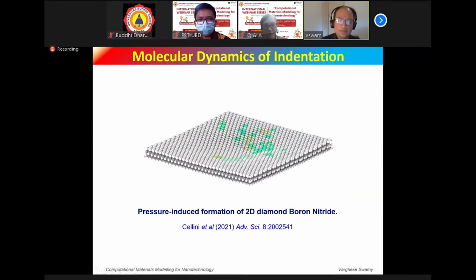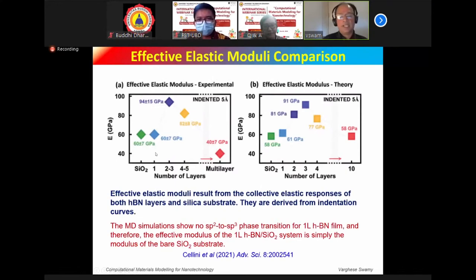You can see that this bonding is metastable. That means that as soon as you release the pressure, the bonding is reversed. It goes from SP2 to SP3 when you compress it, and when you relax it, it comes back to the SP2 bonding. So that's what they have found. And they were also able to compare the experimental effective elastic modulus, because we are talking about a material lying on a substrate, and its variation as a function of number of layers in the experiment.